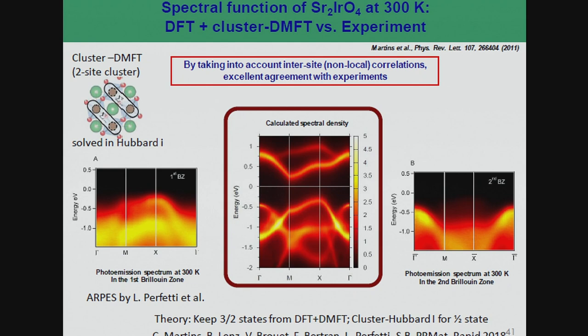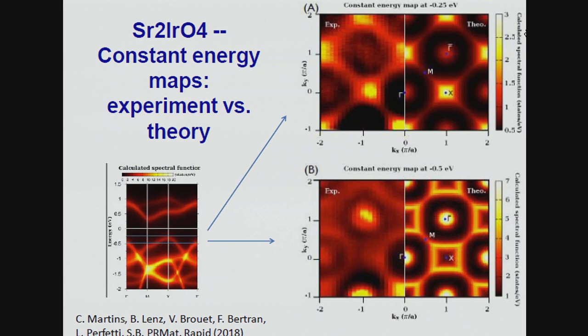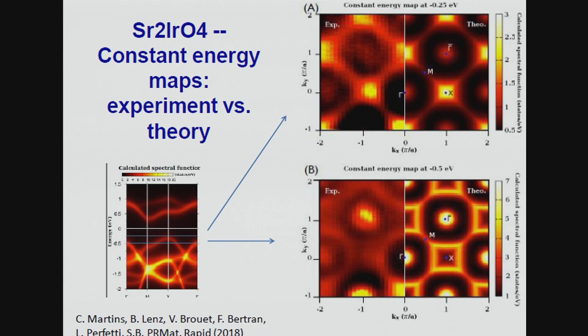Let's extend our theory to include, as a minimal model, inter-iridium fluctuations. We include iridium-iridium self-energy by using a minimal model — a dimer. The minimal cluster is just two sites. And surprisingly, this indeed fixes the problem. The result shows that we now get the very dispersive feature, and the three-half states survive correctly. The details of the spectral function — in particular the dispersion — need this cluster description because inter-iridium fluctuations are important. You can compare more in detail with experiment by looking at cuts: fixing an energy and looking as a function of K. The theory agrees very nicely with the experiment for different energies.